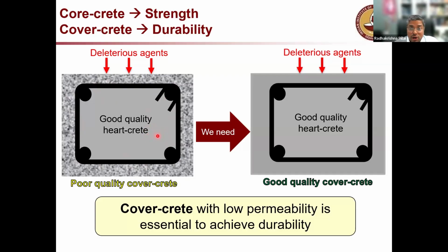Now, if you do not cure the concrete very well, then you have a problem that the surface or the peripheral concrete, you can see my cursor here, red color cursor, the surface of the concrete will be more porous in nature, maybe of poor quality, which will affect the durability. It means if it is poor quality concrete on the surface, what will happen is these deleterious agents like chloride, oxygen, carbon dioxide, moisture, etc. can penetrate through the cover and reach the bar and create problem. Problem means create corrosion.